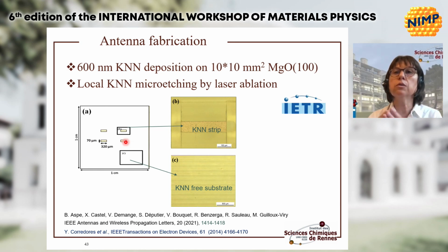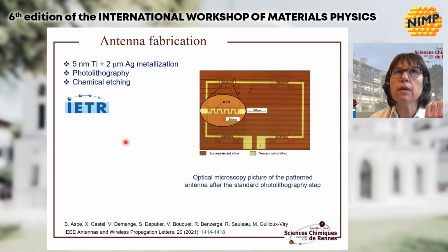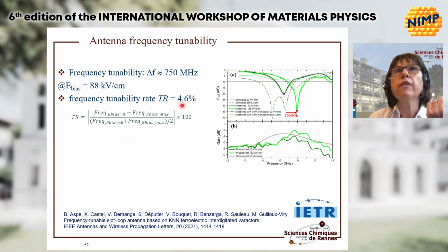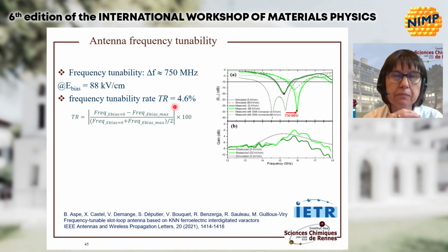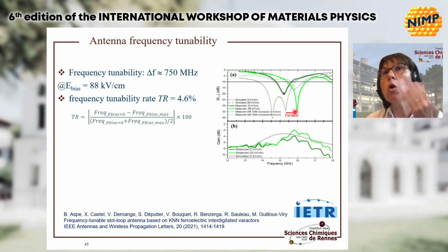But we now have to work on, for instance, antenna arrays in order to increase the gain. And for the tunability itself, the percentage is quite low, but if we compare not the tunability measured like here, but the tunability performance with regard to the electric field, this value is quite high. So to answer more precisely your question, I think that 4.6% can be quite enough, depending on the frequency range. Here, the operating frequency is near 15 gigahertz. That means that here we have more than 0.5 gigahertz.